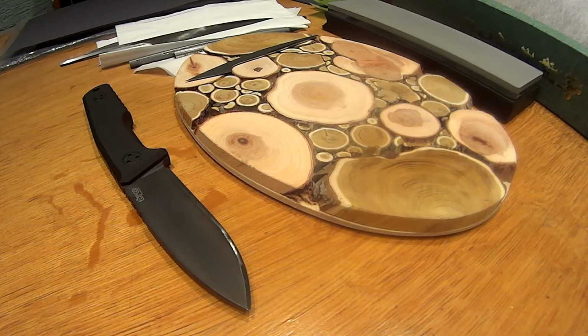In previous parts, I've talked about attributes critically determining optimal application of Elmax, and described some limitations which restrict the use of similar steels for cutting tools that require the highest possible cutting performance, meaning very low edge angles, less than 10 degrees per side, and very thin geometry behind the sharpened edge, less than 0.2 millimeters at 20 degrees total sharpening angle.